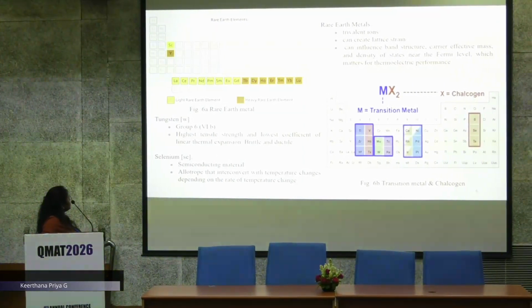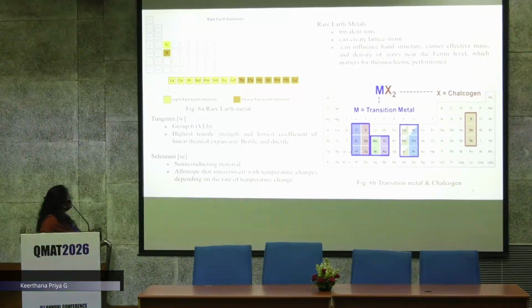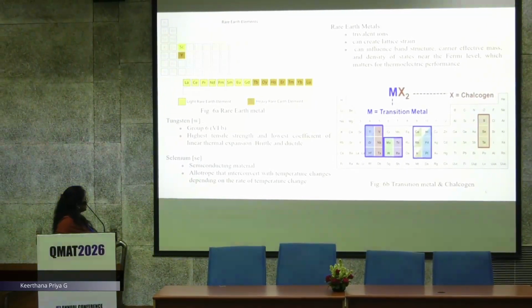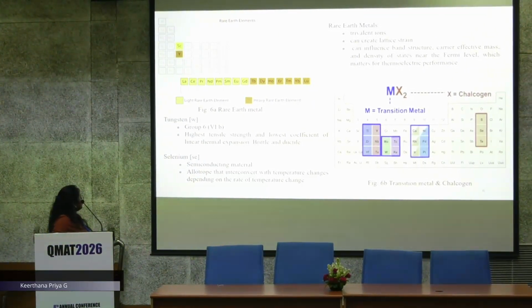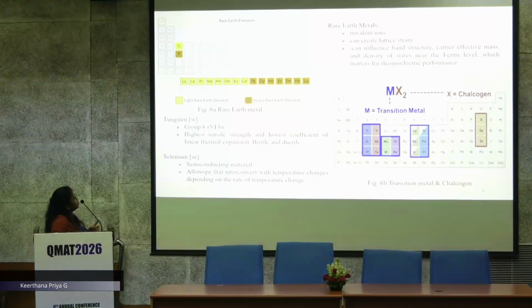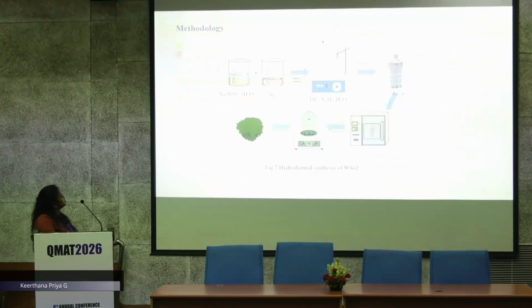Group 6, which has high tensile strength and the lowest coefficient of linear thermal expansion, and selenium is a semiconducting material which can easily convert according to the temperature change. As for rare earth, it's a trivalent compound. They can create lattice strain. This also can influence the band structure, carrier effective mass, and density of states near the Fermi level, which gives better thermoelectric performance.